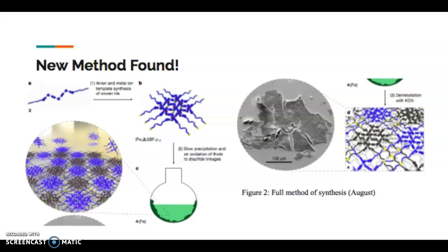they are then connected. And once the grids have been connected into a larger polymer sheet, the ions were then removed using demetallization methods, specifically potassium cyanide in this situation, thus creating a purely organic molecular fabric that was measured to be 4 nanometers thick. But it had a very large surface area, as you can see in this image of the flake that it has.